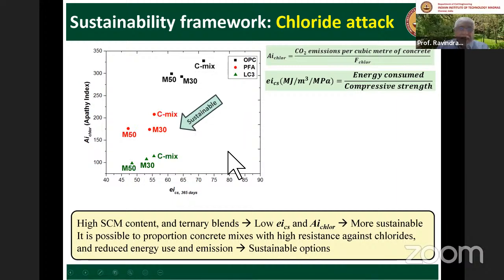What about higher grade concrete? If you go to higher grade concrete, it is more and more sustainable, because for the same strength, for the same cubic meter, you're getting more strength. Okay, so it becomes even better. And the common mixes also have the same thing. So very clearly, higher SCM content, lower clinker content, we can get more sustainability, and especially under chloride attack, LC3 comes out very, very well.